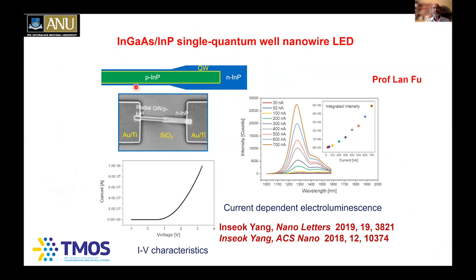And then you can see that he spent a lot of time during his PhD doping this indium phosphide with the P-type dopant, zinc, and then grown the indium gallium arsenide quantum well, that yellow layer here, and then has grown N-type indium phosphide on top of that one and made contacts to both ends of the nanowire, using electron beam lithography. He injects current and looks at the voltage, the IV characteristics. You can see that the IV characteristics show a diode-like behavior.